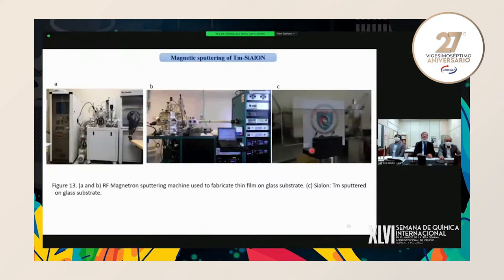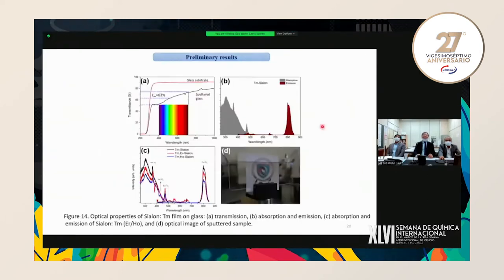Okay, so this is our equipment, our laboratory. We have a magnetron sputtering material. We make this kind of Thulium and SiAlON material as a target material. So we make a target for magnetron sputtering. We coated this Sialon material on the glass.